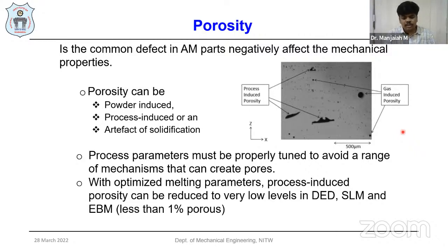We need to optimize the process parameters, which must be properly tuned to avoid the range of mechanisms that can create the pores. With optimized melting parameters, the process induced porosities can be minimized to as low as less than 1% in DED, SLM or EBM. But still there is a challenge in controlling this gas induced porosity.